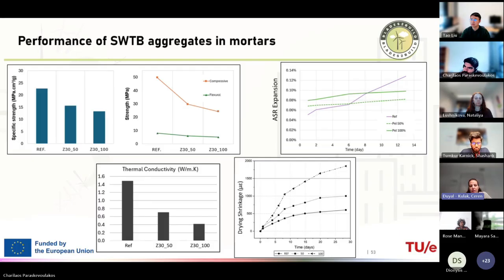Of course, as expected, since the reference mortar is prepared with river sand, it has a higher strength because there is no such high porosity in it. However, it is still comparable. When we have the 50% replacement, we have a strength of approximately 30 megapascal, and if we have replaced 100%, we have 22 to 24 megapascal of compressive strength, and the flexural strength almost remains stable.